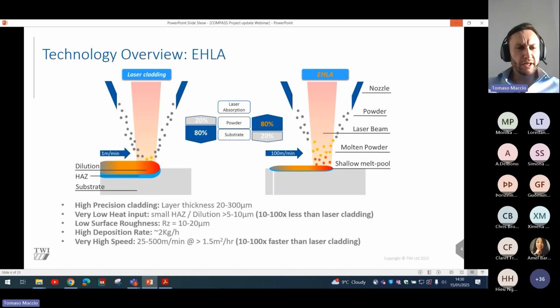So I'll go over very briefly the differences between EHLA and laser cladding. There's a schematic on my left here, I don't know if this is flipped for you guys. On my left, if you can see my cursor, is laser cladding. We have a fairly large dilution zone with laser cladding because the melting is happening on the substrate. This is the powder being fed in here. Melting's happening on the substrate, so we get a really large dilution zone and a large heat affected zone. What that does is, in the melting process, it brings up iron that's in the substrate through the deposit. So in turn, you have to do more layers, so you're not getting iron